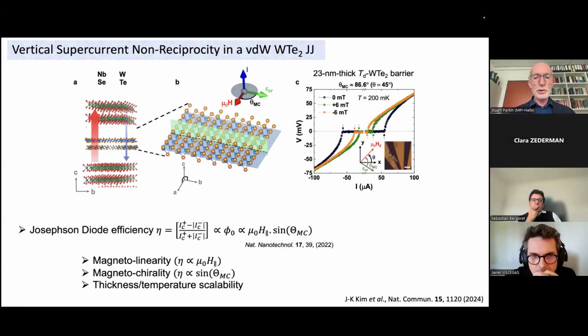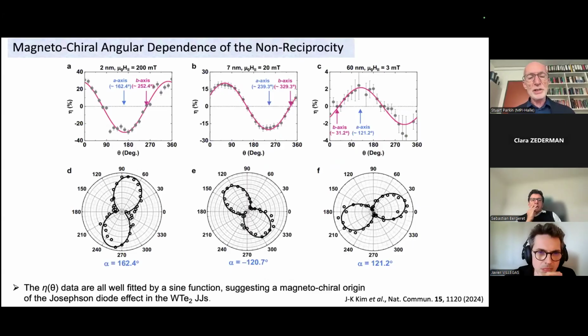What we can do then is we can measure, okay, I'm going to skip this. What we can measure is here we have three distinct all van der Waals vertical Josephson junctions that Jae-Kun has made. And we actually don't know the orientation of the tungsten ditelluride flake before we do the experiment. So he does the experiment and he measures this eta, the efficiency, the difference between critical supercurrents for left and right, in the presence of magnetic field.